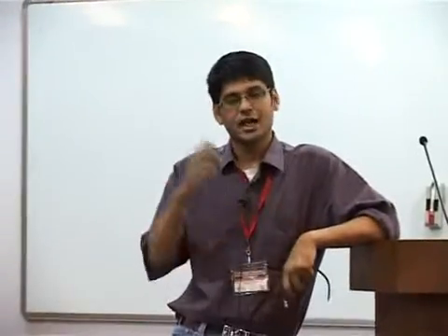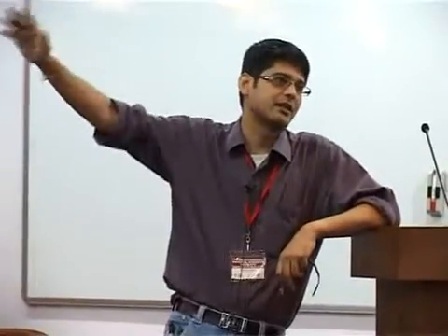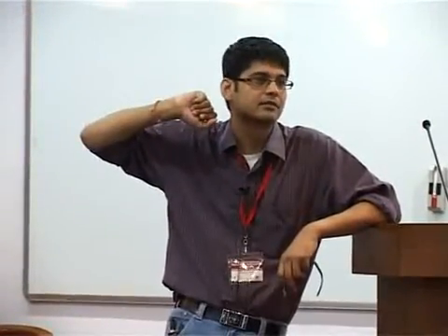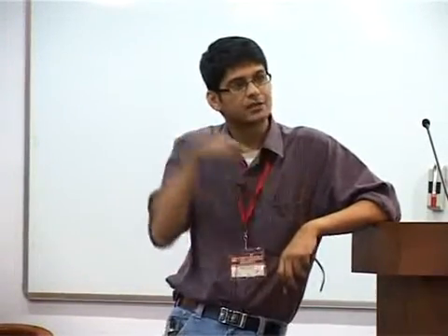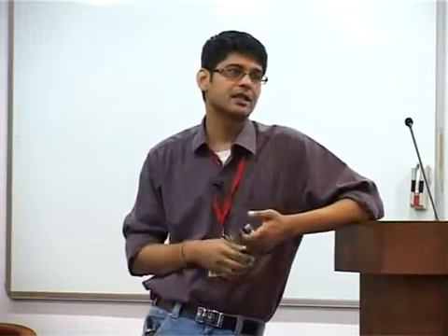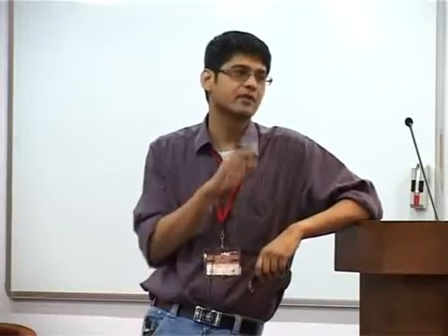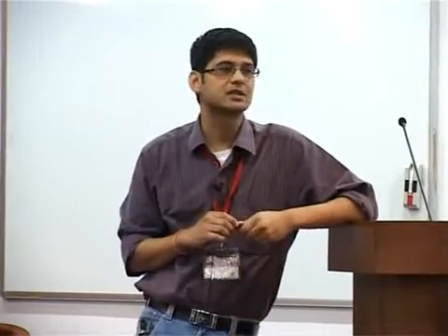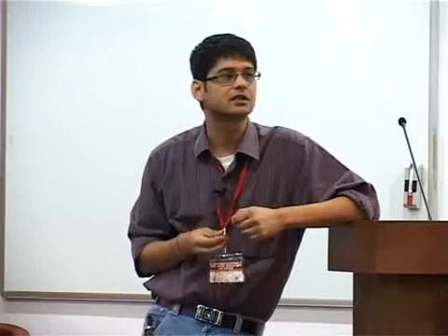So all that I do is, I know my critical field is, for example, at 100 volts per micron. I go up to 90 volts, come back. Go to 90 volts, come back. The third time that I go to 90 volts is going to fail. So every time that I go to 90 volts is actually weakening the system. Yes, so these are complicated time-dependent events which you can actually see up here, but we have not gone into the time-dependent events. Yes, there's a lot of hysteresis in the whole event here.